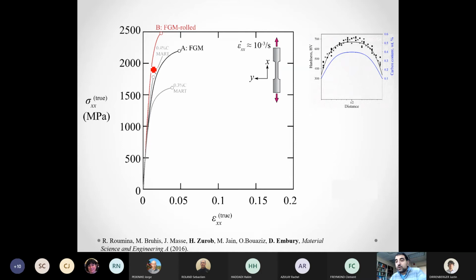And this is an example here where we machined a tensile sample out of the cold rolled material. And you could see it only broke when we reached a stress of about 2.5 GPa. So obviously that material didn't have any big defects. Otherwise, knowing the low fracture toughness of martensite, it would have fractured at much lower stresses. So clearly, the material was not cracked in the initial state. It did not develop tiny cracks as a result of the cold rolling.